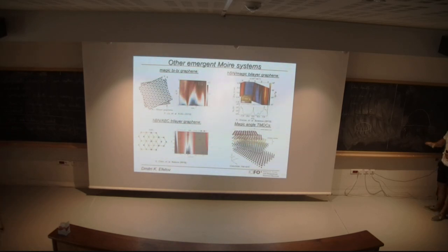With correlations, it's actually slightly different. Again, this is not published, just what I know from discussions. Correlations really seem to have some sort of shape like this, and then they disappear at one point. But interactions around the magic angle are not the strongest. They're somehow stronger even on the sides of that diagram. But yeah, the statistics is very low. Overall, in magic angle graphene, we are talking about 12 devices which were measured among 5 groups or so.